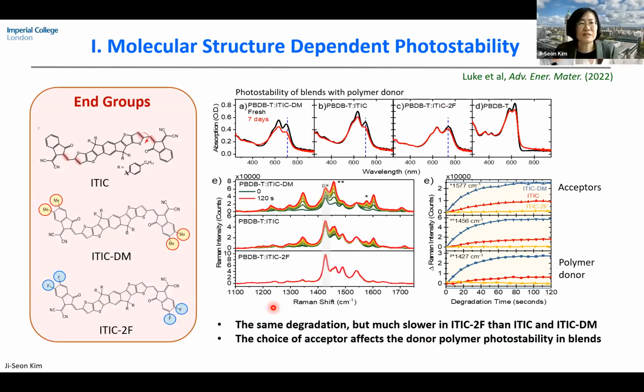Finally, the end group effect. Here I show, as an example, ITIC, changing the end group structure by putting more and more electron withdrawing end group atoms. What we found is that when you change the end group, you don't actually change the degradation mechanism. However, it slows down the degradation. So as you can see, the fluorinated ITIC shows much slower degradation compared to ITIC and dimethylated ITIC molecules. Another interesting point is that the choice of these acceptors strongly affects donor polymer photostability in the blend.